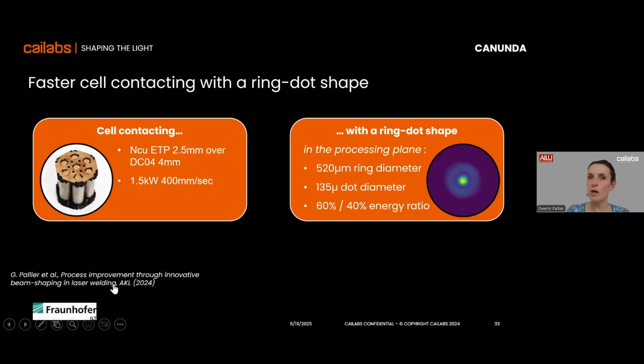Of course, when you do e-mobility applications, you want to do cell contacting. In that case, the whole point was to remove wobbling. It's possible to weld those batteries using a standard beam, but what you're doing is a lot of little circles in order to control your melt pool and have compliant welds. And what we wanted to do was to remove wobbling.